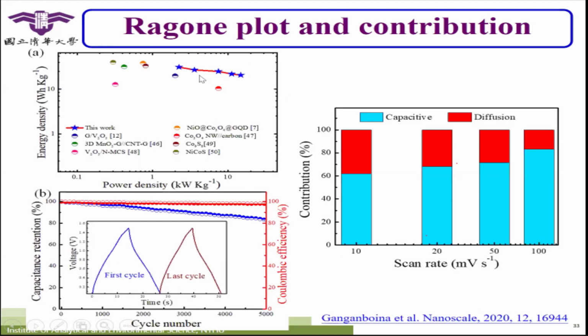So in that case, we can get the Ragone plot here. I mentioned that our goal value is 100 and 100, but at this moment, our value is larger than 10 and 10. That's the essentials for electrode material. Our value actually is relatively high compared to the now reported data here. You always will see their value is here. So it means that when you use graphene quantum dots with some other carbon-based material, the energy and power densities will be relatively high here. You also will see that the retention will be good after 5,000 cycles. That means the discharge will be good.